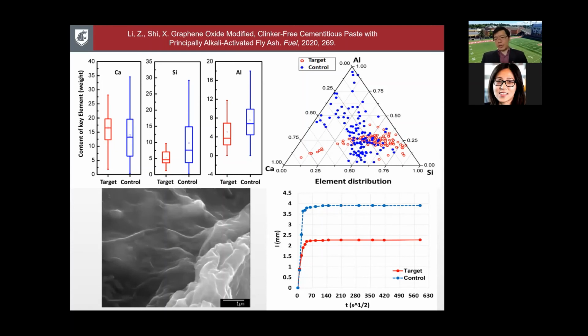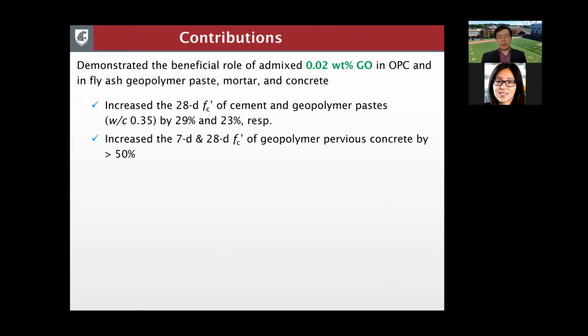And at the bottom right, we see that the water absorption is much reduced due to the admixed graphene oxide compared with the control group. So to conclude, here are our contributions. We demonstrate the beneficial role of admixed 0.02% graphene oxide in OPC and in fly ash geopolymer paste, mortar, and concrete. And the graphene oxide increased the 28-day compressive strength of cement and geopolymer paste by 29% and 23% respectively for water binder ratio 0.35.